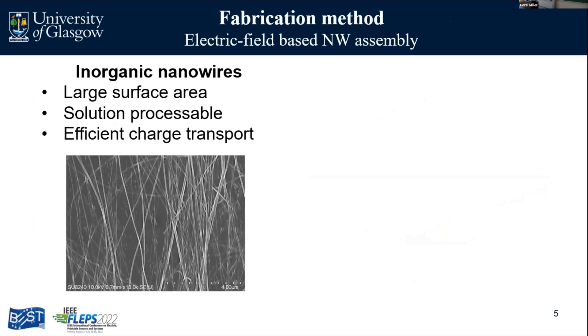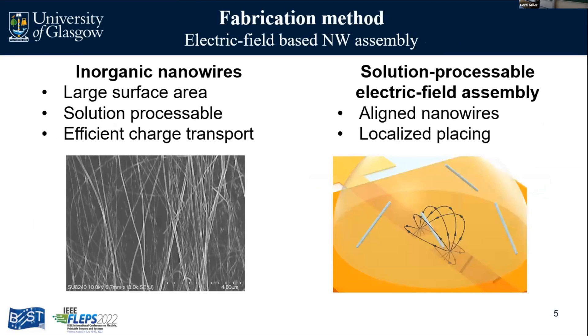Why are we using V2O5 nanowires? First, nanowires have a large surface area, which gives a great improvement in sensitivity. They can be solution-processable, which really allows us to scale up fabrication. We also have efficient charge transport. However, working with nanowires is not that easy — we need to assemble them, align them, and place them in specific locations, because we don't want nanowires everywhere and we want to align them to achieve good electrical performance.